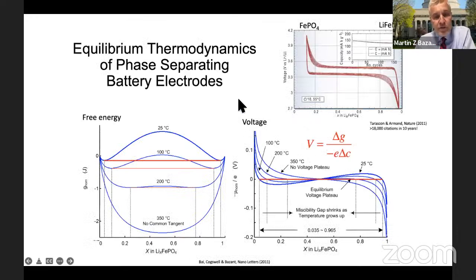So first, I have to tell you a little bit about phase separation. If you look at the voltage of lithium iron phosphate versus a reference like lithium metal in this case, as a function of the composition or the content of lithium, it's hard to read here, but this is x in Li_x FePO4 in the upper right. As you go from left to right, you're filling the particle with lithium. And what you see is a voltage plateau on insertion and extraction of lithium. What that means is that at either end of that plateau are stable phases of lithium at certain concentrations. The way to see that is shown on the left here.